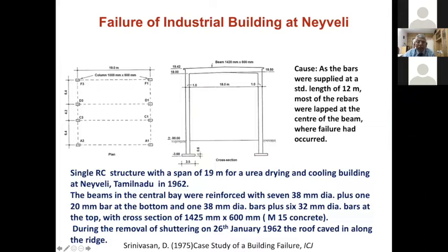So this happened in 1962. The beams in the central bay were reinforced with 7-38 diameter plus 1-20 mm diameter at bottom and 1-38 mm diameter plus 6-32 diameter bars at the top with a cross section of 1425 by 600 mm. The concrete was M15 because at that time M15 was allowed. During the removal of shuttering on 26 January 1962, the entire roof caved in along the ridge. It is because all the bars were lapped at the same point.